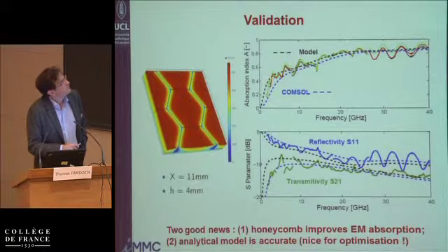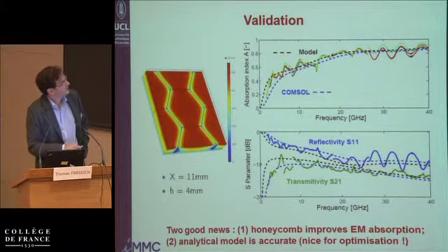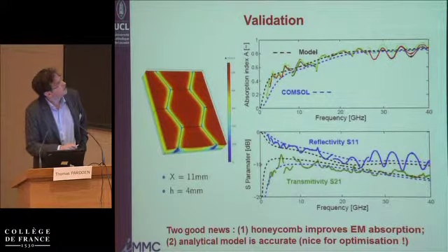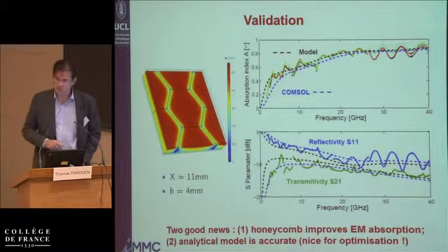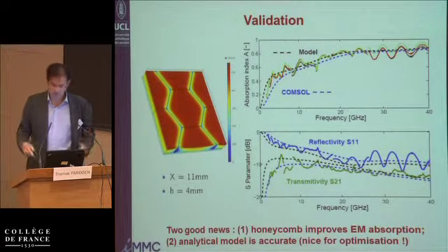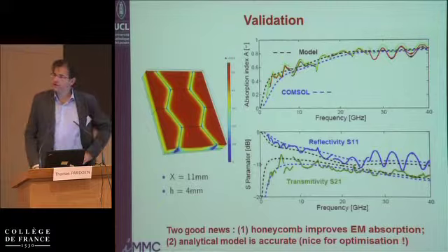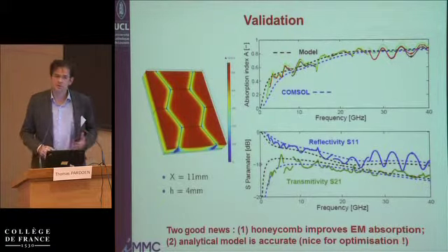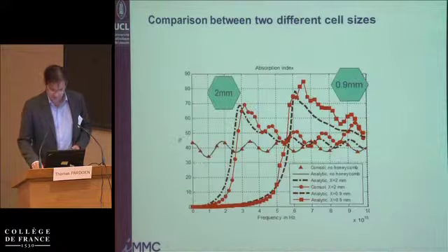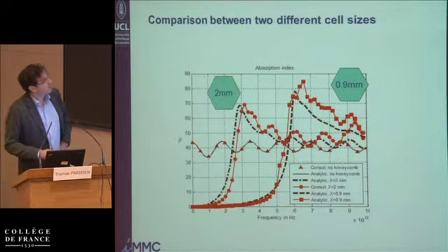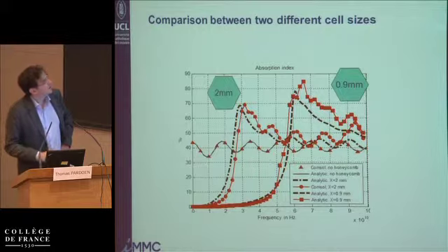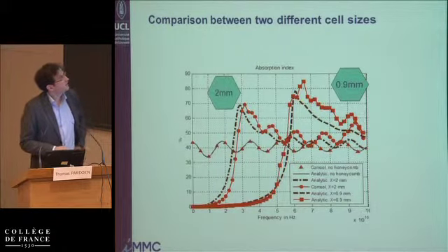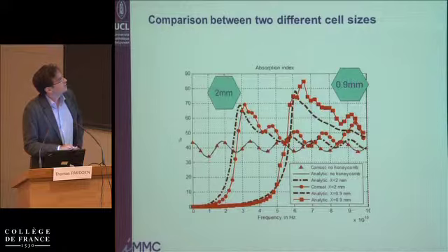And you see here, very good absorption for this size of honeycomb in a range here of above 3 or 4 gigahertz. Below 3 or 4 gigahertz, depending on the size of the honeycomb, you have the cutoff frequency, and there is no effect anymore of the honeycomb, and basically then waves are transmitted. So these are other examples where it's a combination of analytical modeling and finite element models for the absorption here for a 2 millimeter honeycomb and for a 0.9 millimeter honeycomb size.